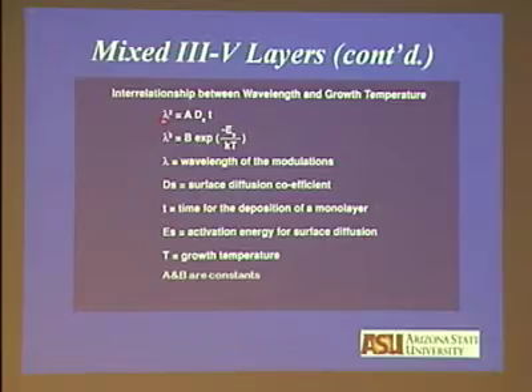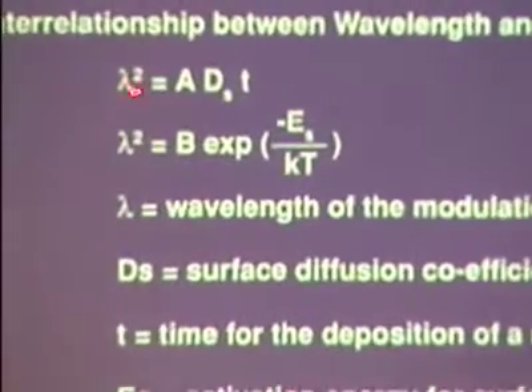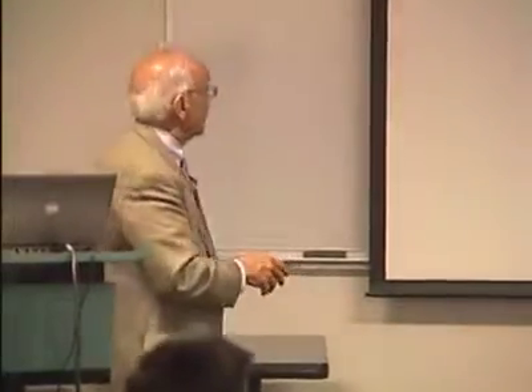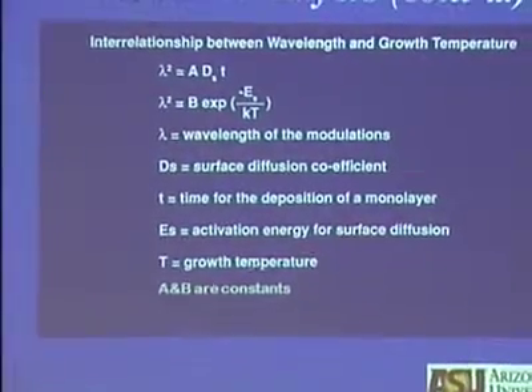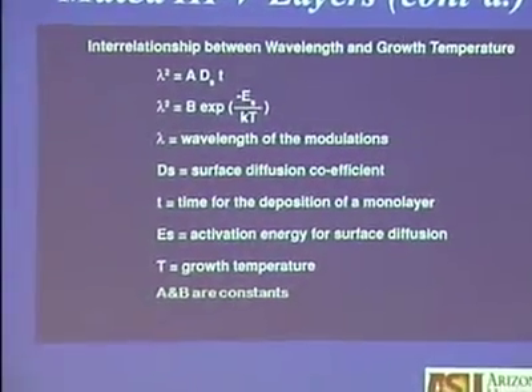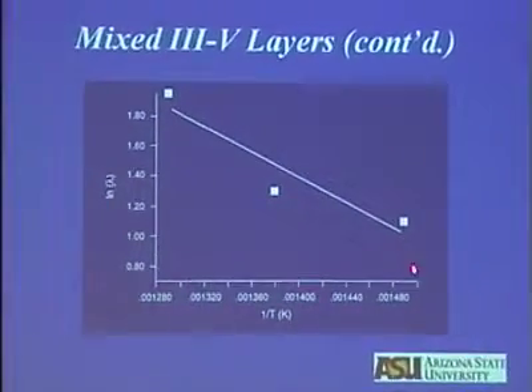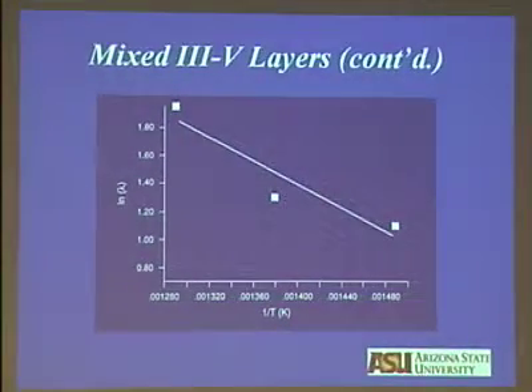You can write a simple expression: the modulation wavelength is related to some constants, A, the surface diffusion coefficient, and T, the time we take to deposit a monolayer. Once the monolayer is deposited, the diffusion of atoms cannot occur. This is the assumption we made. And you have the activation energy for surface diffusion, the growth temperature, and A and B are constants. So we measured the wavelengths of modulation from the diffraction patterns, then correlated them, and the fit is fair, not bad. What it is telling you is that we can measure the activation energy from it, 0.25 eV, and that correlates with the migration of arsenic on the surface of these layers. So we can correlate that.